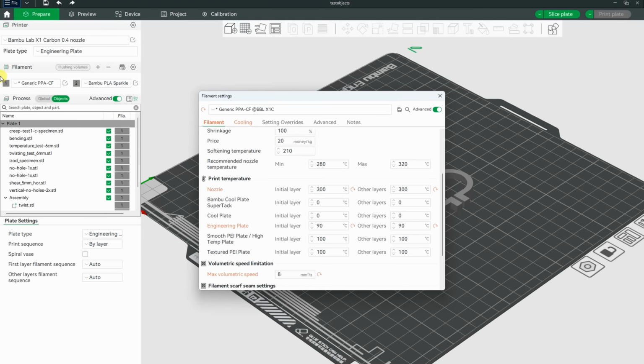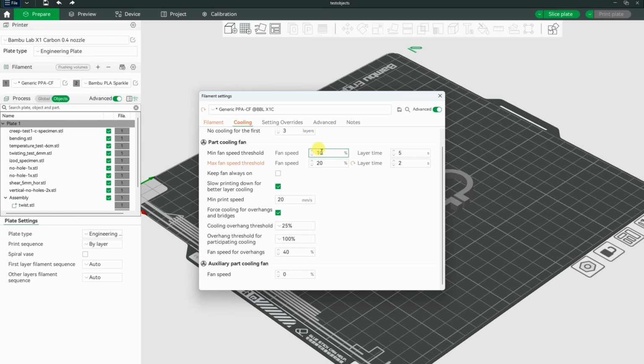Now I don't need a temperature tower because everything will be printed at 300 degrees Celsius. Generic PPA-CF profile, 300 degrees Celsius, 8 is the flow, and I reduce the part cooling to between 10 and 20%. Printing with the carbon fiber version is even easier. The second group with some parts which will be annealed too.